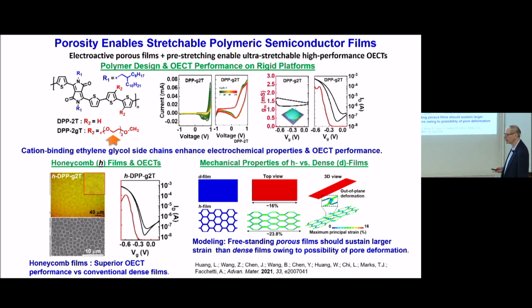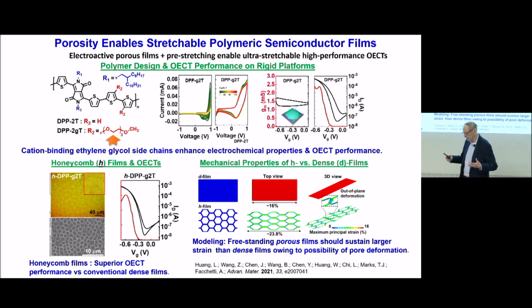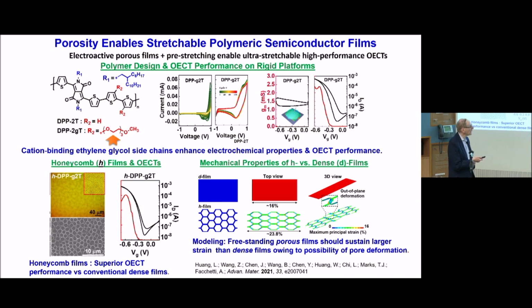So what kind of a polymer do we want? Well, this polymer has to have redox properties. I create holes in the polymer with the electrochemistry, and those are, of course, electrons, and they conduct. But we're going to do more than that. As I create these positive charges or negative charges, counter anions have to flow in through the porosity. And so we put these ethylene glycol groups, polyethylene glycol. Those actually are known to facilitate cation mobility.